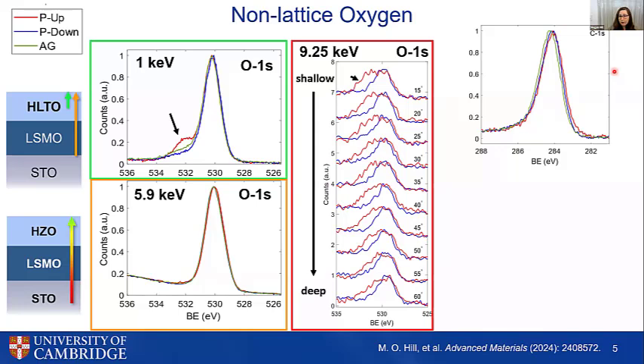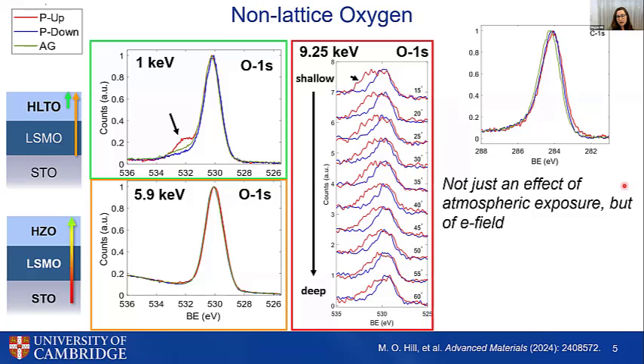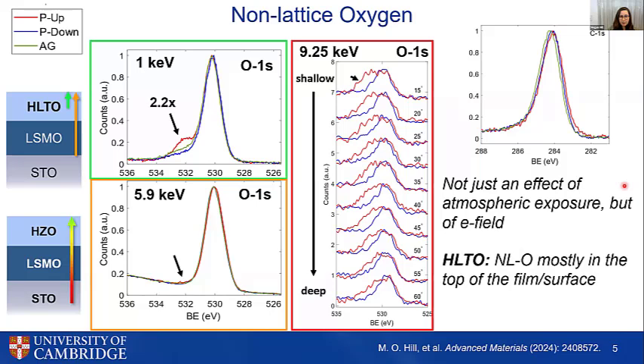And also, if we look at the carbon 1s spectra at 1 keV for HLTO, we can see that between all of these conditions, there's not much of a change in the carbon peak. So this suggests that this is not actually an effect of atmospheric exposure, but actually of the electric field that we have applied before our measurements. This peak has about a twofold increase for the P up condition, both for HLTO and for HZO.